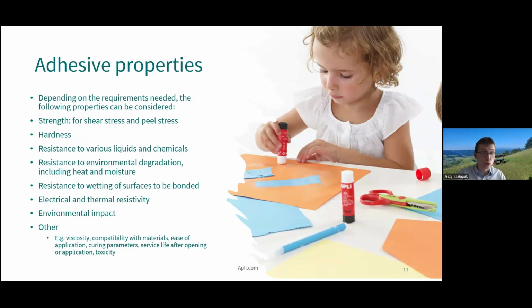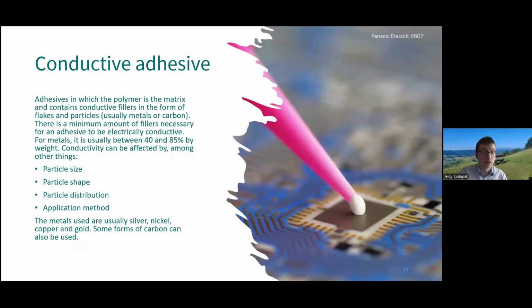Although it is crucial to remember that the shear strength of the adhesives is limited. And it is even more limited when we consider adding conductive particles into the carrier. Let's be honest, the more particles we add, the weaker the adhesion will be. It's quite logical because we are reducing the amount of polymer, which is the sticky part of the conductive adhesive, responsible for the adhesion and for the cohesion.